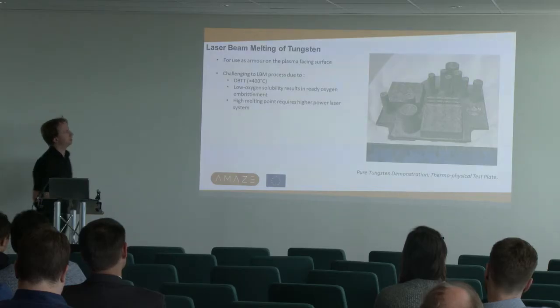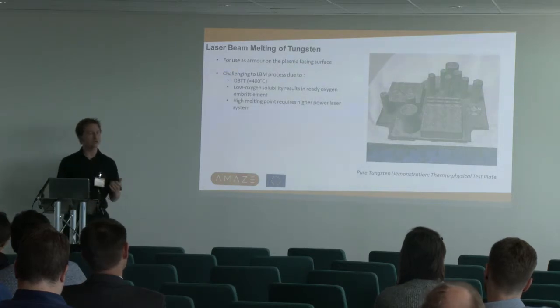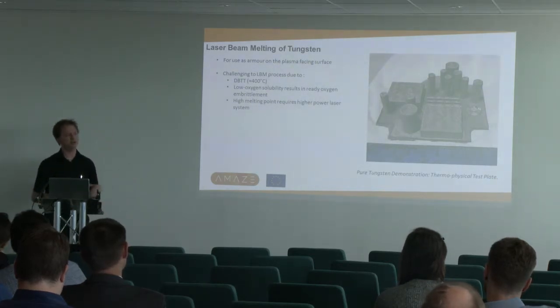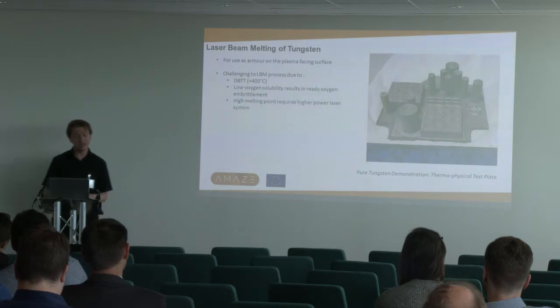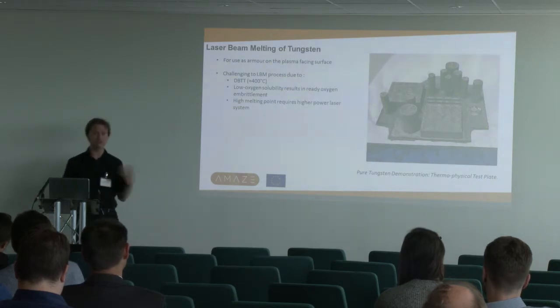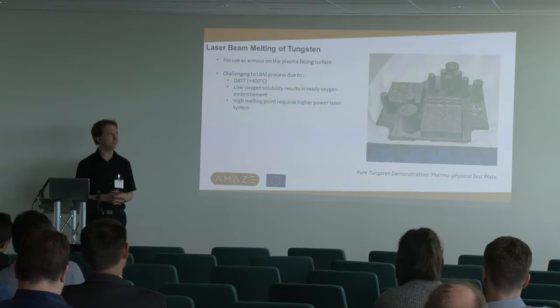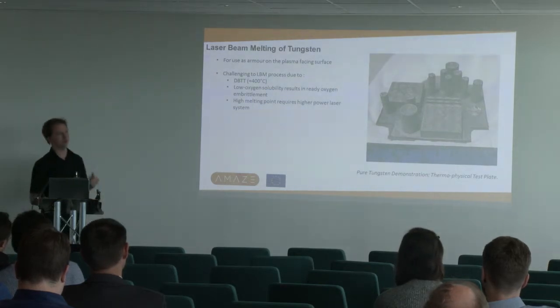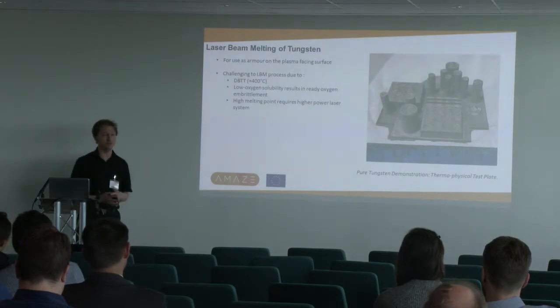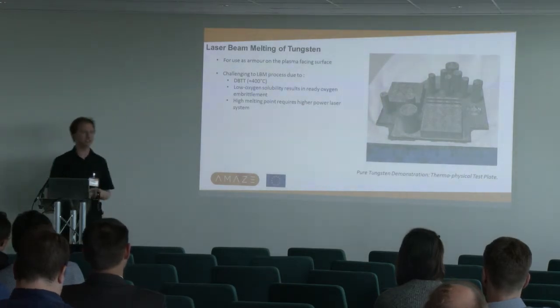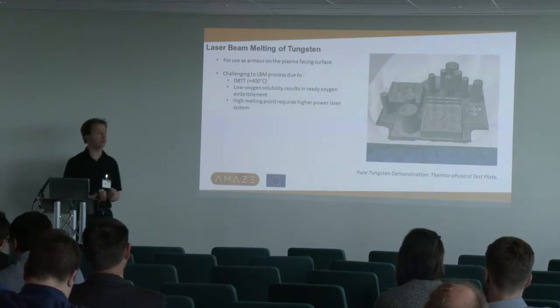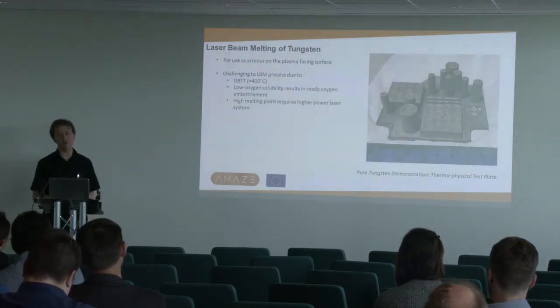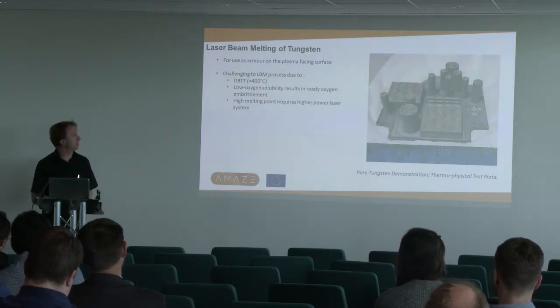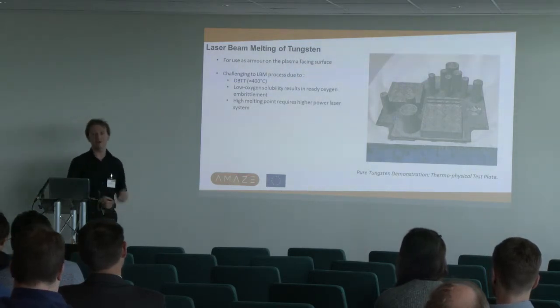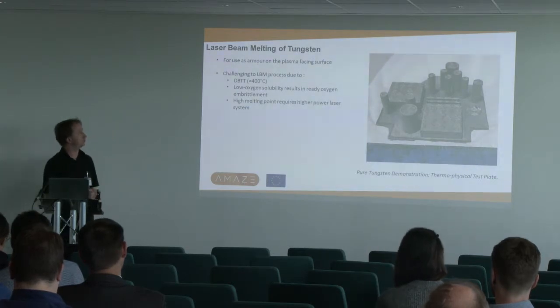Moving on to the tungsten, which is, I guess, the current focus of our work. Some of this is, as I said, part of Amanda's work, and it's ongoing. It's a very challenging material, again, as I'm sure you're aware. It's got this ductile brittle transition, so it's not really ductile until, and again it depends on the oxygen content, but if you want a really rough ballpark figure, a few hundred degrees, 400 degrees maybe. Above that, you start to get some ductility in the material. Below that, it's brittle, so it's going to crack at room temperature under residual stress. It's very prone to oxygen embrittlement and has low oxygen solubility, so the oxygen tends to go to the grain boundaries and form brittle regions there.